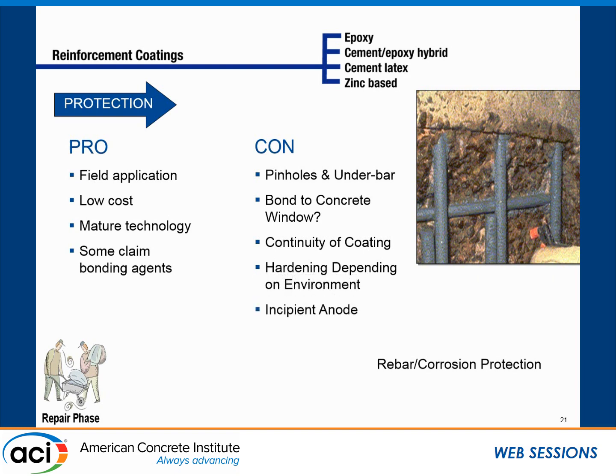Do they do anything about the incipient anode, the ring anode, the halo effect? That's where the steel that was corroding was the anode of the corrosion cell, and right outside where it was corroding is the cathode. But I don't see anything happening at the cathode. So I excavate out the hardened concrete and fill the hole where the anode was, that makes it cathodic, and it moves the anode to right outside the repair. By making it more cathodic, I may make it worse.